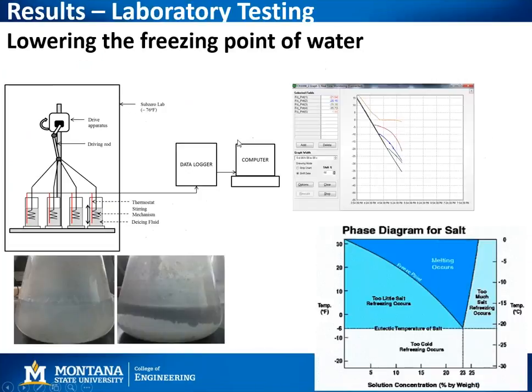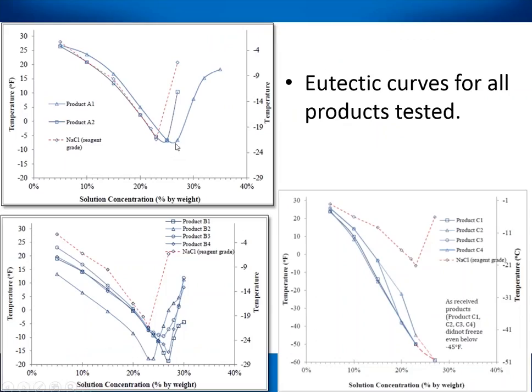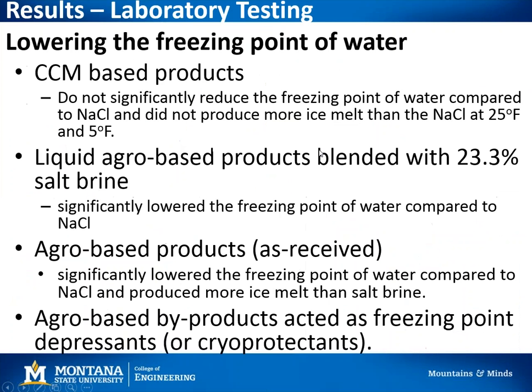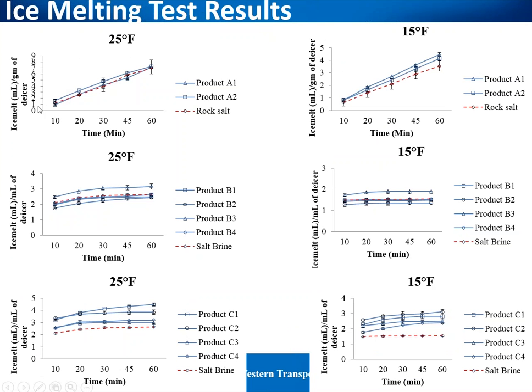iSlicer is product A1, and here's our eutectic curve. So what we see here is the eutectic temperature of product A1 is on track with all the other complex chloride salts, which is -5 to -6 degrees Fahrenheit. Now, with that being said, we also found that the ice melting capacity for these products continued, even at 15 degrees, past an hour. And that's really where I recommend that additional testing is, while these products may not have the lowest eutectic temperature, they seem to work for long periods of time. And knowing how long that product can work is very important.